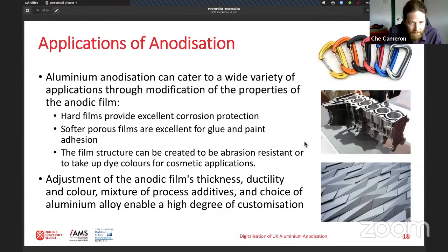So there's a lot of different applications for anodization, and this is due to the fact that you can have a very wide range of properties from that oxide finish. So you can have a hard film for excellent corrosion protection. You can have those softer films that are very, very good for glue, paint, and dyeing. And you can basically modulate the properties of your anodic film by changing your process additives, your process parameters, and the alloys that you're using. So it really means there's a wide range of applications for anodization.